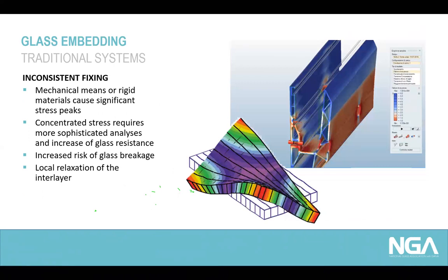So just to go much deeper into the detail, if we talk about mechanical fixing systems, we always have a situation of inconsistent fixing. Mechanical fixing systems are usually based on puncture stress, concentrated stress caused by rigid materials, and this is also causing peak stress in the base shoe and the glass materials. It mainly increases the risk of glass breakage for the glass unit itself, so that requires that concentrated stress is comprehensively analyzed in the verification of the glass railing system, and that requires also an increase of glass resistance.